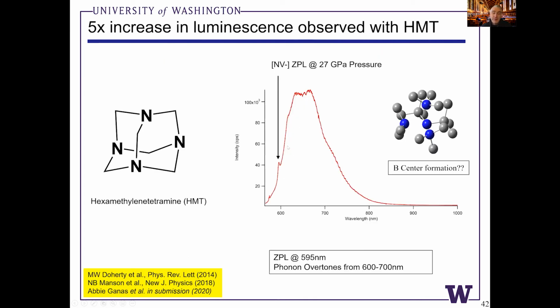We've also seen a 5-fold increase in the photoluminescence of these diamonds. So they have much more emission than the undoped control samples. This is a high pressure spectrum showing the negatively charged NV center shifting to high pressures. This is at about 27 GPa, but we're still unable to answer the question, have we made B centers? This is one question that we're trying to answer.